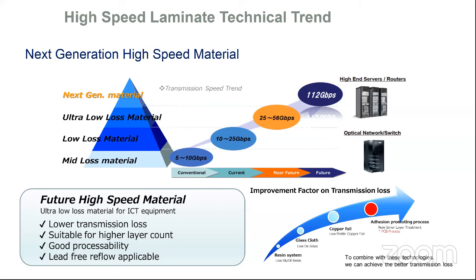And in days gone by, we were under the school of thought that rougher was better from a laminate or prepreg adhesion. But we know that if we allow the adhesion promoting process to roughen up the copper, we've lost all the benefits of seeking out lower profile copper. So the industry is rapidly working and developing newer adhesion promoting systems, getting to the point where we're nearly at no topography after oxide treatment.